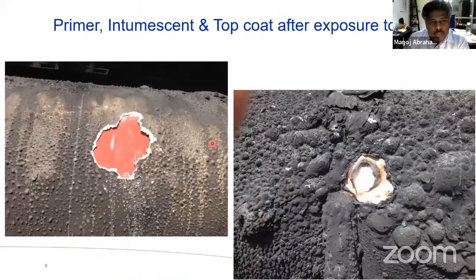You can see this, right? So you've got your primer. This is our primer, 17410, and then your intumescent and the top coat. Here you can see that some of the intumescent has started to char, but the remaining intumescent is there to protect. If additional heat comes in, this would start to char as well. And this char forms an insulating low thermal conductivity foam, thereby protecting the underlying structural steel.